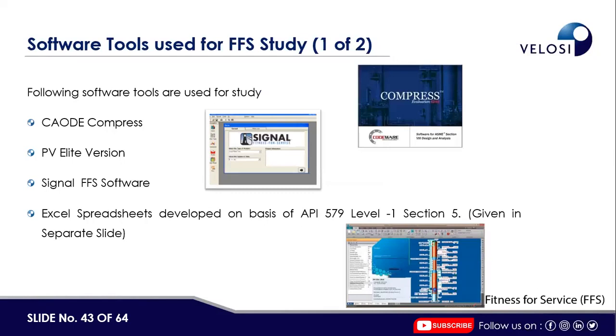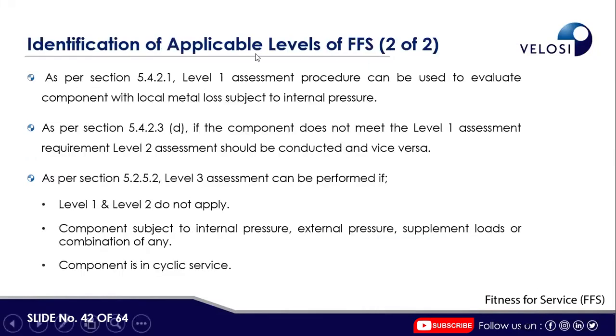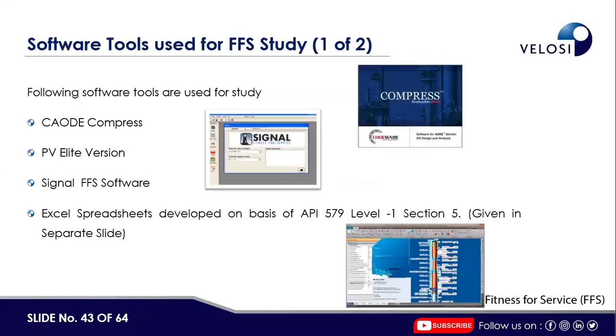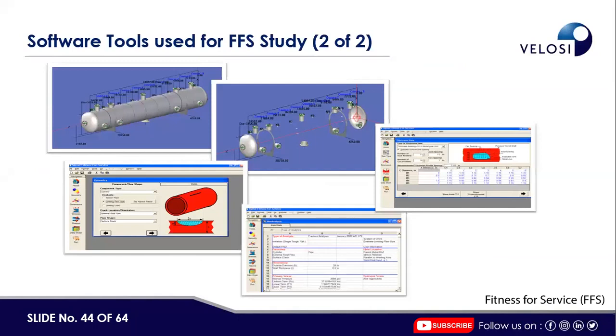Now, following API 579, if the number of cycles is more than 150 for a component in cyclic service, then finite element analysis is required to be conducted in accordance with ASME 8 Division 2. It's not listed here. So the following software tools are used by us: Caesar, Compress, PV Elite, Signal FFS. Excel spreadsheets were also used for level 1 assessment. And these are the models which are used in 2 or 3 softwares. The first ones are from PV Elite and the lower ones are from Signal.